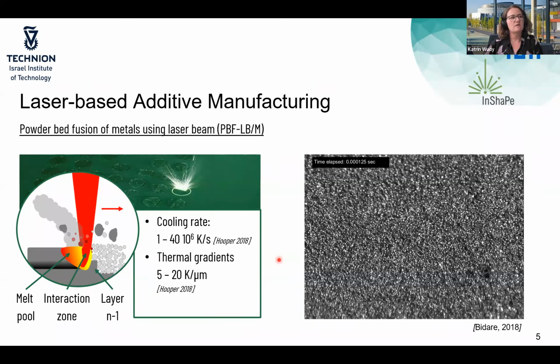And the question I would like to raise is, how does this change of the energy input away from this Gaussian beam profile to different beam profiles in powder bed fusion influence processing and maybe also part properties? So what is known in literature is that typically we use Gaussian beam profiles, but there are some investigations with fixed non-Gaussian beam profiles, and they have shown, for example, with fixed ring-shaped beam profiles that these researchers were able to create larger process windows, less defects, larger melt pools. So that was the key idea and setting the scene.